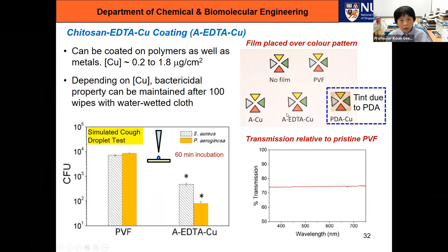And in all cases, if you look at it visually, it's hard to see the difference. But we did run the transmission spectrum, and we find that this coating, the chitosan EDTA copper coating, the transmission is 75% of the PVF coating. And this is much better than this one, which is polydopamine copper. It is very easy to make, but unfortunately, polydopamine has a brownish tint. So you will give a brownish tint to the coating.